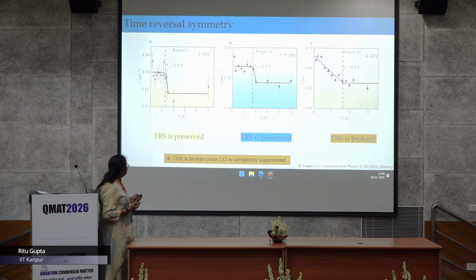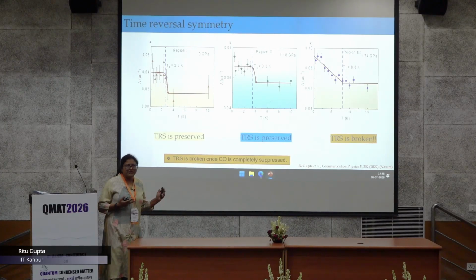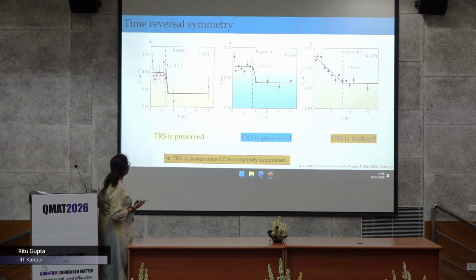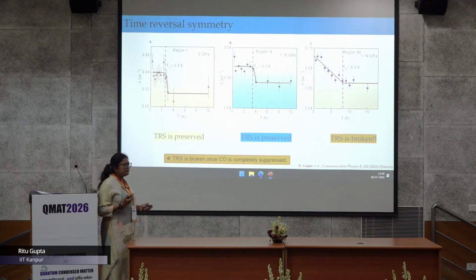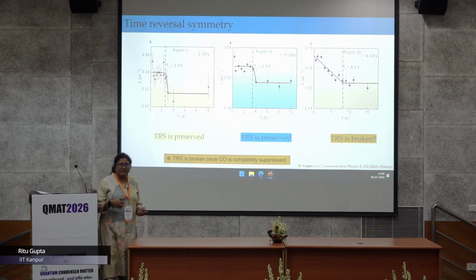Okay, so basically we carried out zero field experiments in three different regions of the phase diagram. And here we see some step like feature around the superconducting transition temperature, but we know that the charge order phase in these compounds is breaking time reversal symmetry, so there is a magnetic field already present.